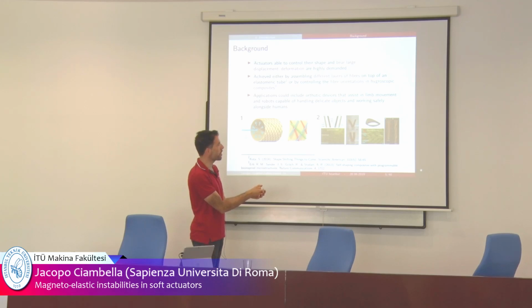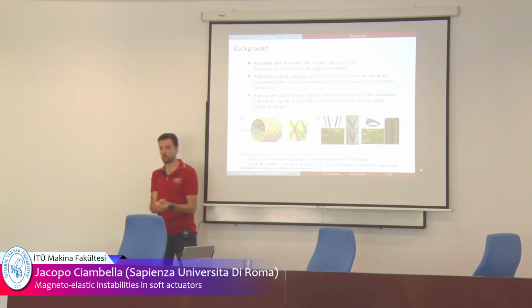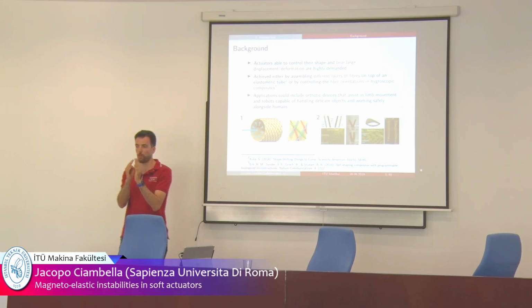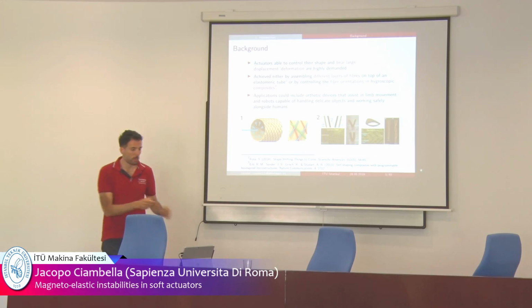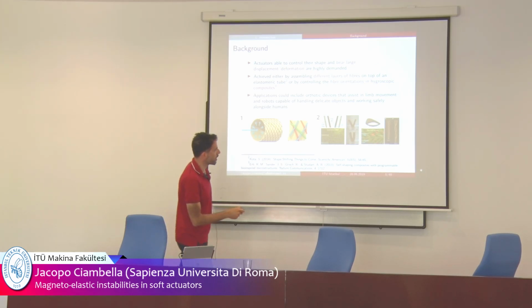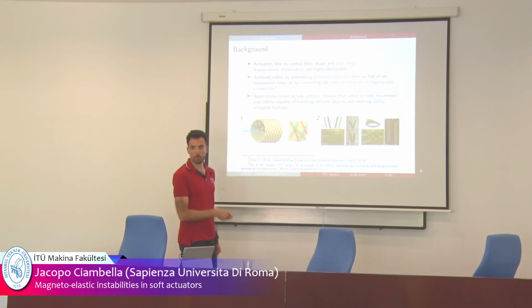Why will it bend? Because you have fibers in the different sections of this small strip oriented differently. Okay, so different stiffness, and then that will give you this bending effect. And with another distribution of the fibers, you can get twisting. Okay, and always by diffusion of a solvent inside the material, of humidity or solvent.